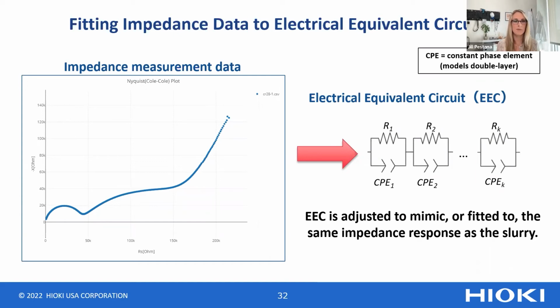Here on the left, we have a plot of the AC impedance measurement. On the y-axis, we have negative X, which is the imaginary impedance, and on the x-axis, we have R sub S, which is the real impedance. And there we have an analysis, the data we get from the slurry analyzer showing the conductivity, the properties of that slurry. This can be fitted to an electrical equivalent circuit, very similar to a common way of analyzing battery EIS data. There you have resistors and a constant phase element in parallel. Because between those particles there's a double layer, it acts as a capacitor. And then you have the resistance for the electron transfer as well. So that models each of those different electron transfers.